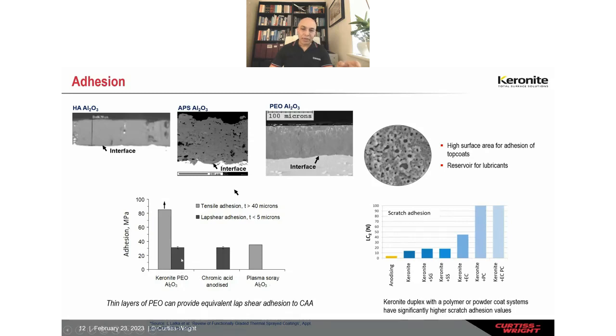And here, the dark gray columns are for a PEO coated thin layer, typically 3 to 4 microns, used as a pretreatment. And that's from the lap shear test, okay? If you see, the adhesion values are very similar to chromic acid anodizing. So does it mean that we can replace chromic acid anodizing as a pretreatment? Possibly, yes, we can. And it's already been used a lot. When we use this PEO as a thin pretreatment layer and apply a subsequent secondary layer, for example a paint or a powder coat, your critical failure load for adhesion becomes extremely, extremely high. It's very, very resistant to scratch.